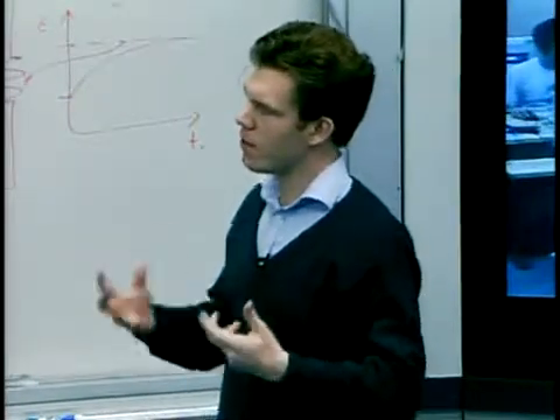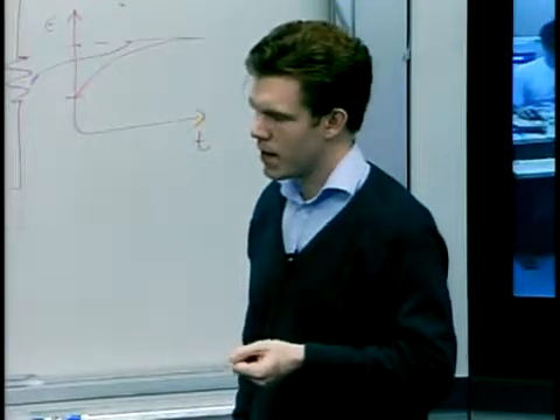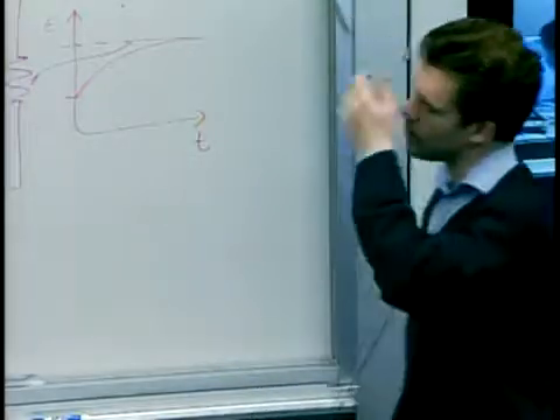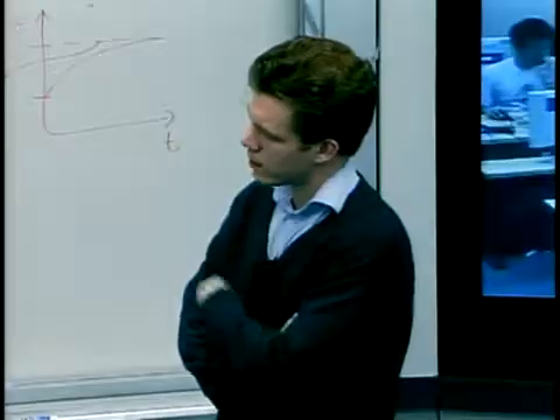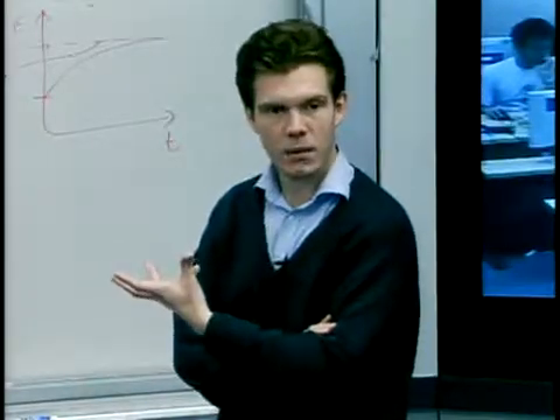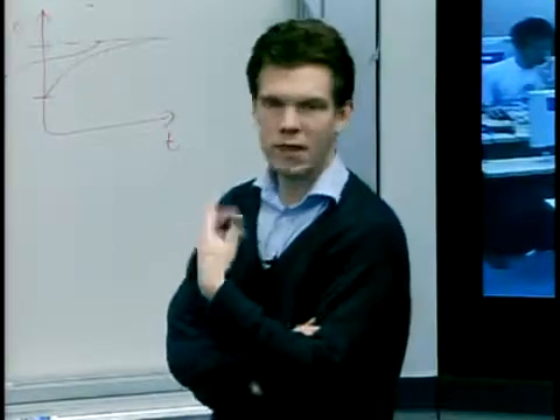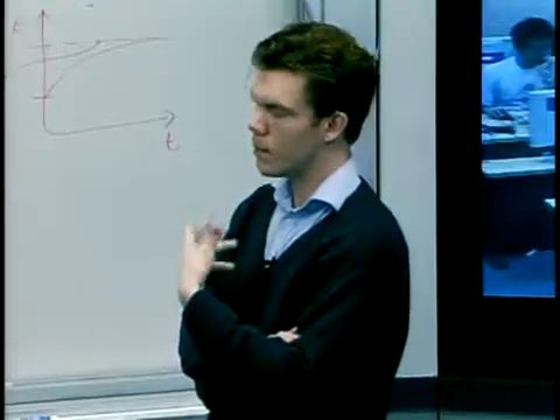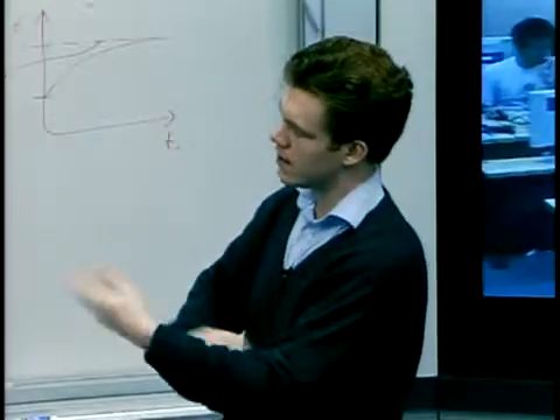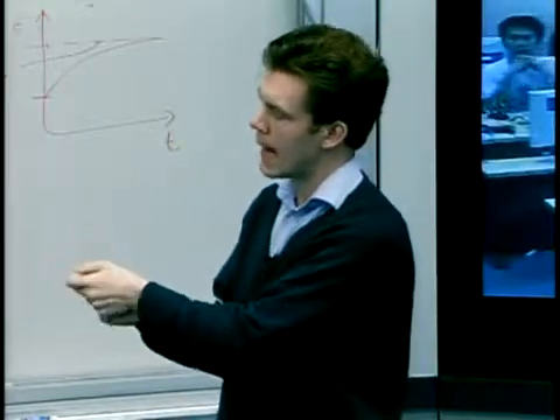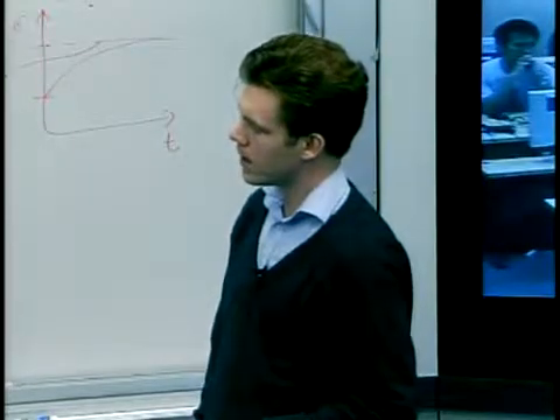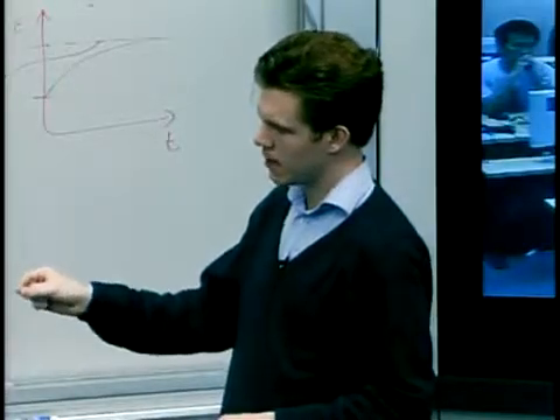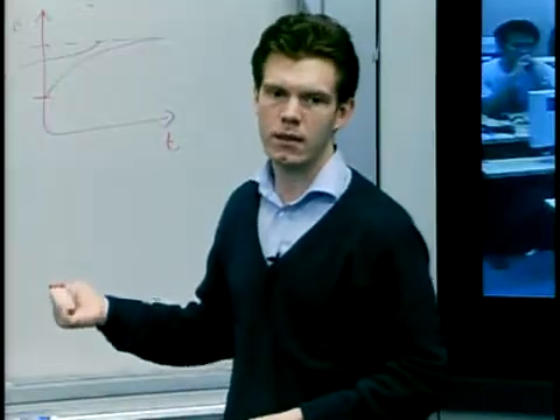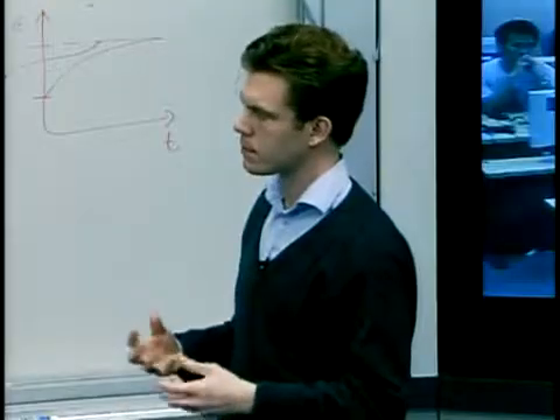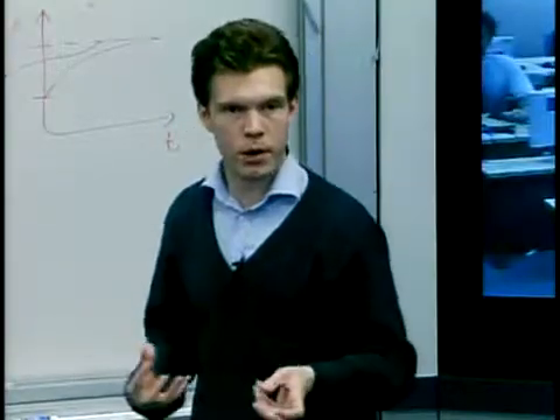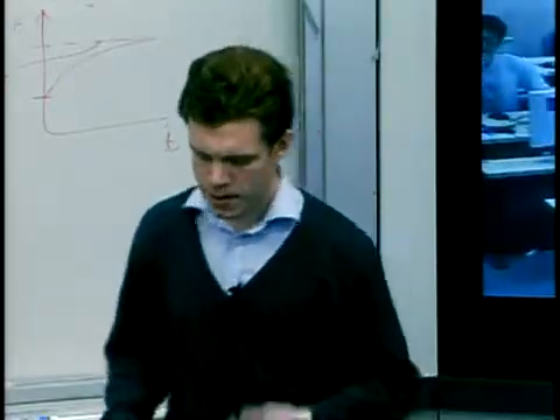So we're definitely in a region where plastic flow is significant, is important, and what we see. These are at the top experimental data, 3D plot of the measurements taken using optical interferometry. On the left for less than a minute holding time, loading duration, and on the right when we left that load in place for 10 minutes. So you can see that obviously over time, the narrower features start to fill, and the simulation to a reasonable extent has captured that. And in fact, the shortcoming of the simulation is that it underestimates how quickly the narrower features fill for the parameters that we fit, and so that is definitely an imperfect model, but it's pretty useful, I think, for getting a first cut of a simulation.